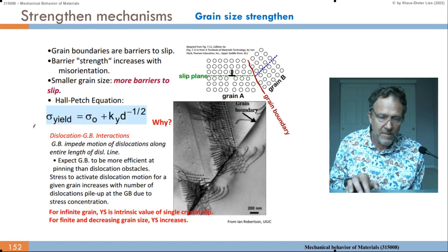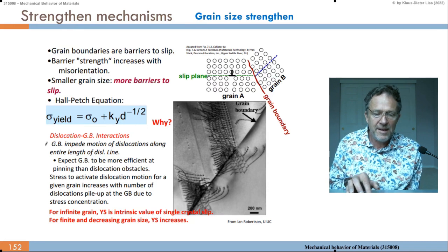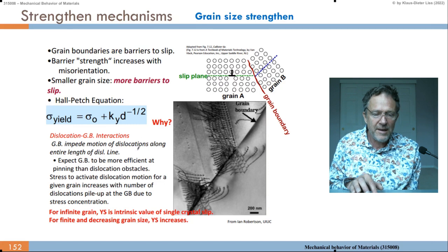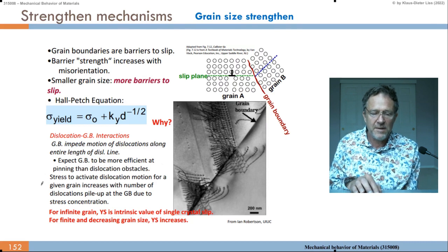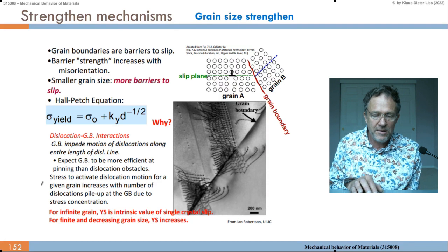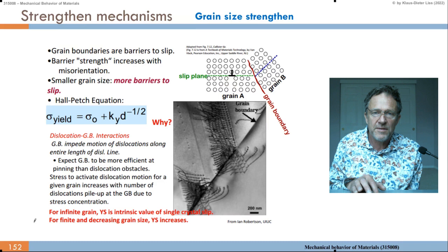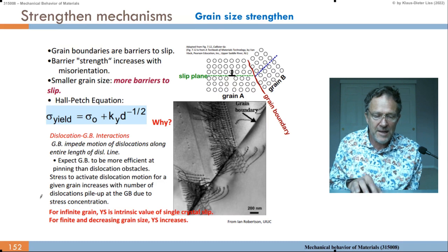Dislocation grain boundary interactions. So the grain boundary impedes motion of dislocations along entire lengths of the dislocation line. Expect the grain boundary to be more efficient at pinning than dislocation obstacles. The stress to activate dislocation motion for a given grain increases with the number of dislocations piled up at the grain boundary due to the stress concentration. So that resumes a little bit what I explained in the slides before and in words.